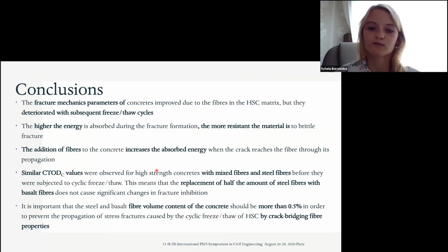In conclusion of my research, the fracture mechanics parameters of MB2 and MB3 series of concretes improved due to the fibers present in the high-strength matrix, but deteriorated with subsequent freeze-thaw cycles. The higher the energy absorbed during fracture formation, the more resistant the material is to brittle fracture. The addition of fibers to the concrete increased the absorbed energy when the cracks reach the fiber during propagation. The freeze-thaw cycling leads to the destruction of concrete with mixed steel and basalt fibers. The fracture mechanics parameters of MB3 series of concrete were significantly deteriorated.